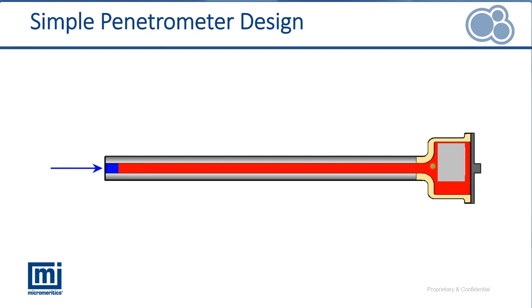If we know that empty capacity, and then we put the sample in here, we surround the sample with mercury at the point where we just fill the penetrometer, we can determine the mass of that mercury by just weighing the assembled penetrometer plus sample in mercury. And again, we then can calculate the volume of the sample, volume of mercury being displaced by the sample, and get a bulk density. I mentioned earlier that we could determine densities. This is how we do it.